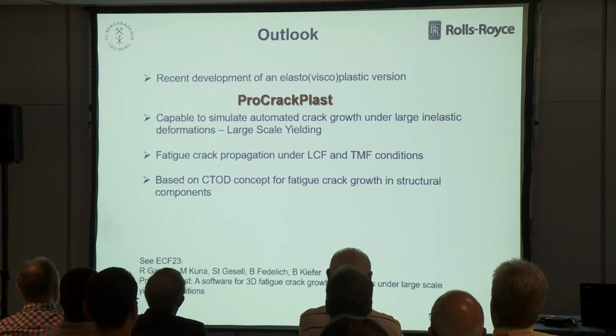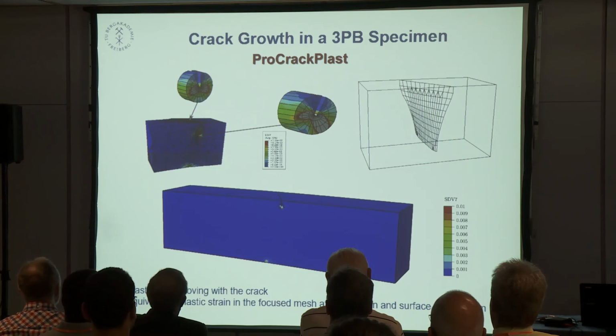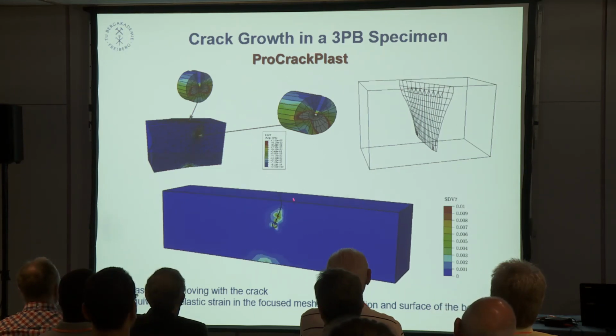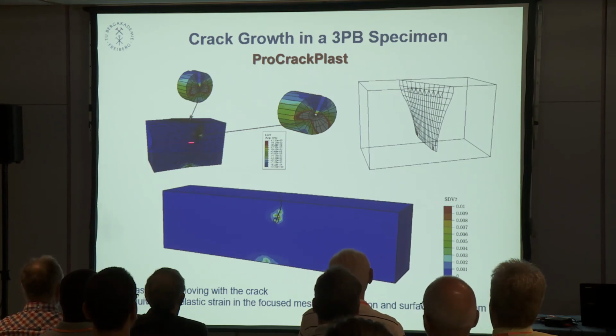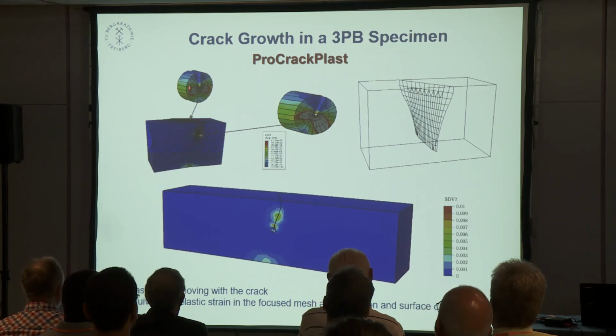And we can no longer stay with the K factor, so we use the CTOD concept as a crack tip measure for crack growth processing. Here you see one of the first examples. It is exactly the same beam with the inclined crack, but now what you see here are the plastic zones which move with the crack. So we can tackle this, and here you see a cutout of the plastic zones in the inner and the plastic zone at the surface. Here you nicely see the mode mixity which occurs here.